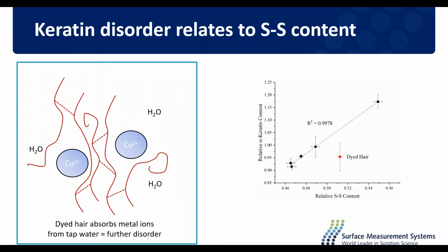And these metal ions have been shown to interrupt the electrostatic bonding between the keratin elements, and this leads to a reduced tensile strength and a depressed melting point for the alpha keratin as measured by DSC. So that can go some way to explain why we're seeing such reduced order in our dyed sample while it still has a relatively high disulfide bond content.